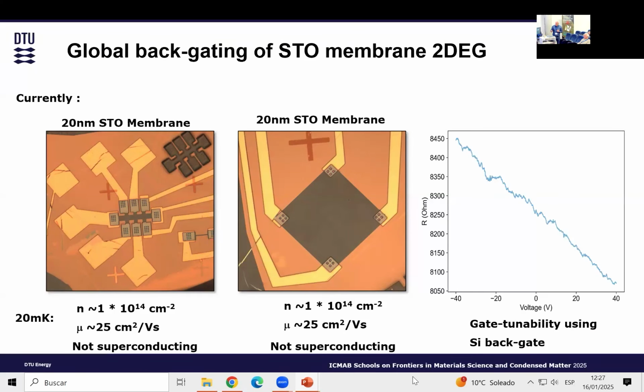Nonetheless, because we are putting it onto a substrate which is conductive, we tried to backgate it, but it's very difficult to backgate the material because the carrier density is quite high. So we are now trying to reduce the carrier density and optimize the mobility, in order to see whether we can get at least superconductivity as other people have. So we just want to replicate the same idea.